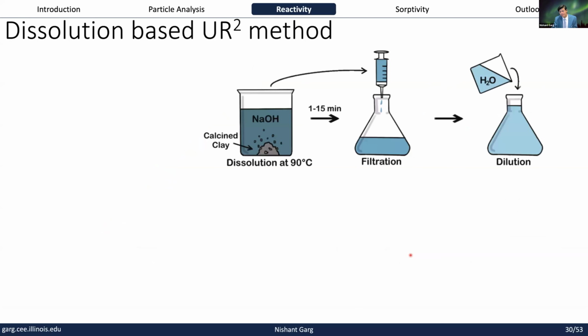So one of the things we wanted to think about here is whether we can develop something around dissolution, because the basic assumption is that if something doesn't dissolve, it doesn't react. If something dissolves, it will react to some extent in a cementitious system. So what we came out with is a very simple method where you just look at dissolution. We don't look at precipitation. So it is dissolution far from equilibrium, with a very high liquid to solid ratio.